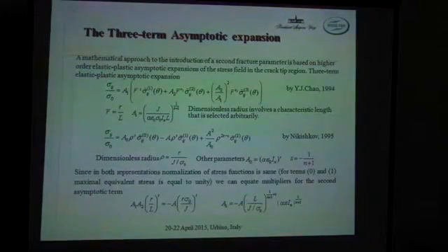A mathematical approach to the introduction of a second fracture parameter is based on the higher order elastic-plastic asymptotic expansion of the stress field in the crack tip region. The three-term elastic-plastic asymptotic expansion was proposed independently by Professor Chao and Professor Nikishkov. So these equations contain singular and non-singular terms. And this equation is very similar.